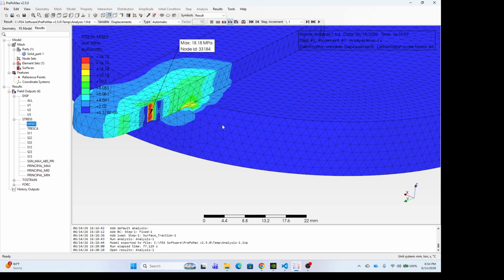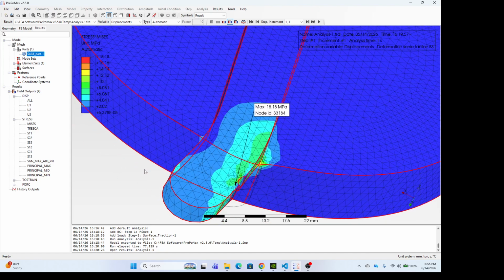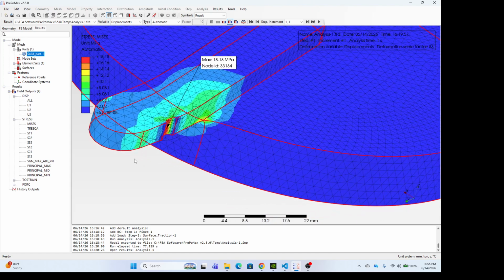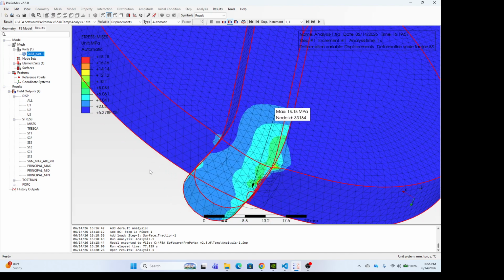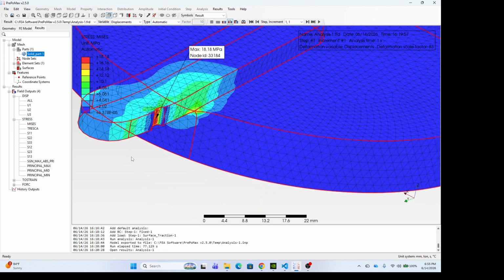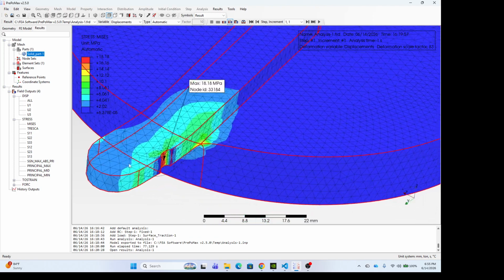It's basically highlighted that standard ductile polymers would undergo local necking, microyielding, and stretching under these conditions. And ductile stretching is a failure mode for security seals, as it makes it easier to cheat the cap past the bottle threads without physically cracking the indicator band. So this, as you can see here, only bent the band itself instead of actually snapping it. And this is clearly not enough force for the band to have a semblance of a snapping indicator.